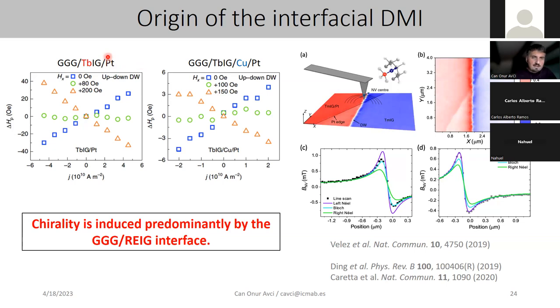And we said, okay, maybe platinum is giving the DMI. But that was also not the case, because when we disconnect platinum from the garnet with a copper spacer, DMI was still there and still strong. From this study and some follow-up studies that we have done, we have understood that the Dzyaloshinskii-Moriya interaction was coming from the substrate and garnet interface, so the GGG and iron garnet interface, rather than the top metallic interface. And this was also corroborated with some parallel studies from ETH Zurich, who also did some additional nitrogen vacancy center measurements on domain walls, and they also show that the DMI is coming mostly from the substrate interface and not from the metal interface on top.